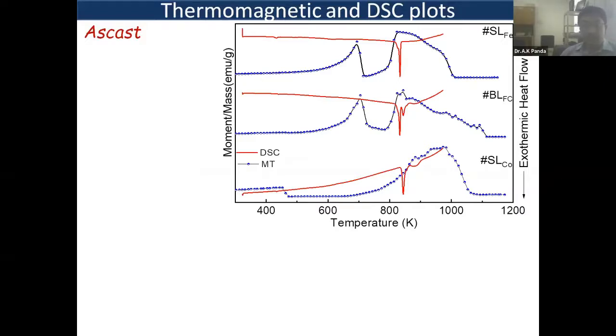This is a plot of moment against temperature for the single layer iron, single layer cobalt, and the bilayered iron cobalt alloy. That is the bilayered ribbon. So you find a change in moment like this, and the red ones are your DSC, differential scanning calorimetry, and the blue ones are the magnetostructural transformation temperature. The very first blue line that you see, the drop, is the Curie temperature, and after that it rises up due to the rise in moment and subsequently falls down.